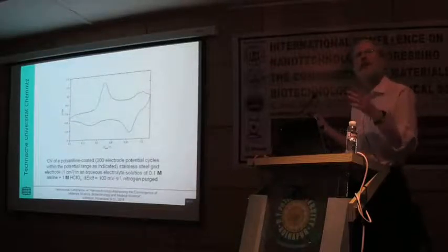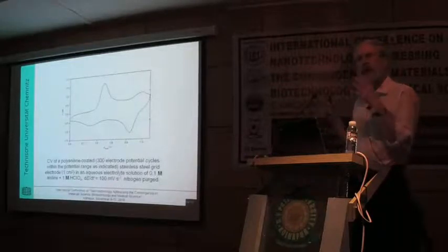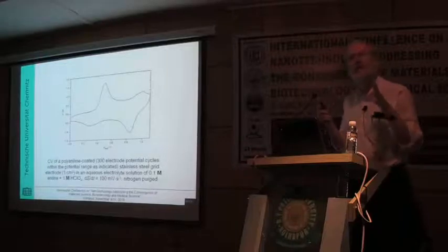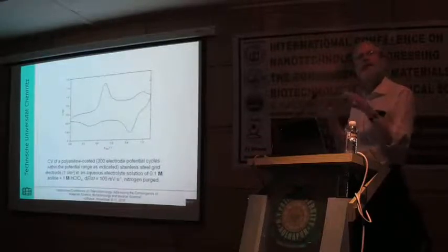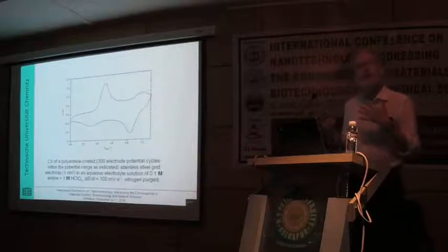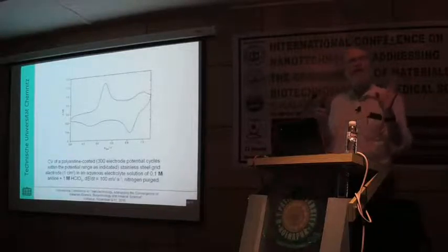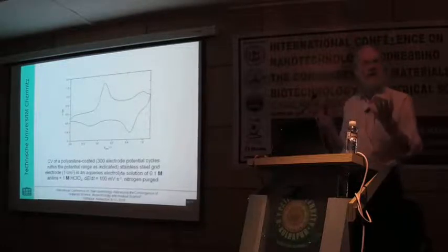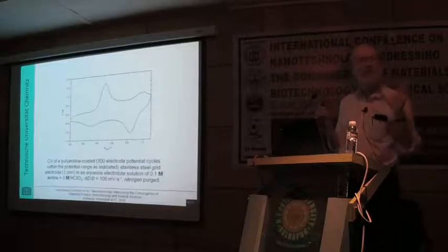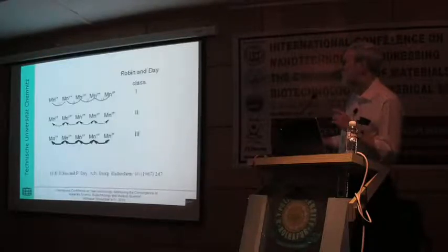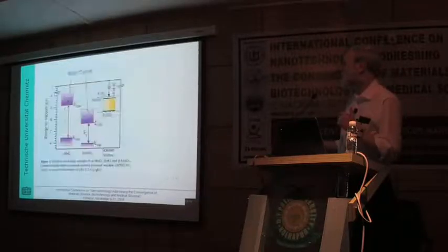The shape of the response depends on the status of hydration. So if there is a lot of water between the manganese species, the behavior is different as compared to a very dry material. And the water molecules in between the manganese species in such a layer of manganese hydroxide can be correlated with the response. So if the material is very dry, for whatever reason we have not yet understood, and we are now asking the theoreticians, the electronic interaction is not as effective. Whereas in the case of a hydrous material like the ruthenium hydroxide or the manganese oxide, the electronic interaction seems to be, for whatever reason, much more efficient and much more effective, resulting in this image which we saw last, and resulting accordingly in this pseudo-capacitive current response.